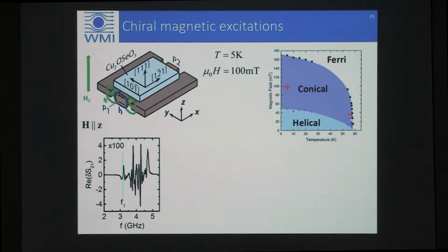And these resonances are actually magnetostatic modes, but not of a sphere, but of a cuboid sample, meaning that the demagnetization field is not uniform in the sample, so it's not possible to calculate them analytically anymore, but you need some numerical code to get spectra like this.